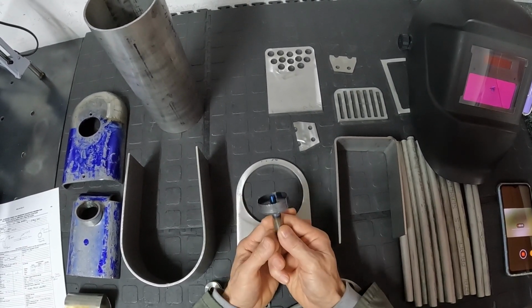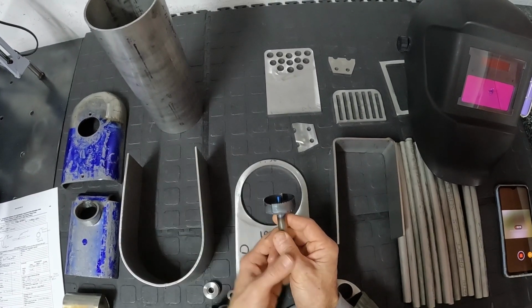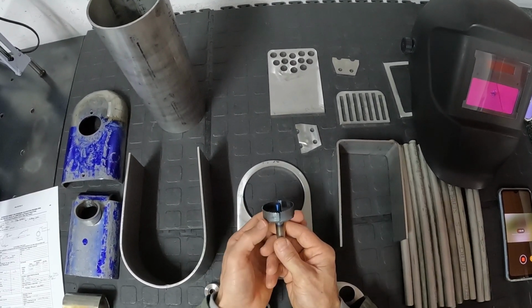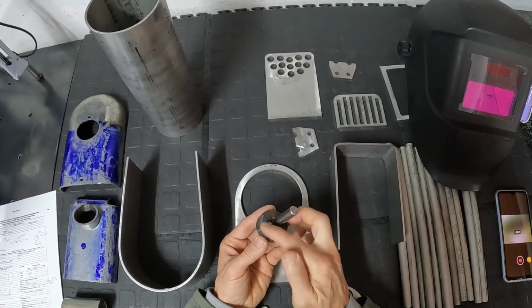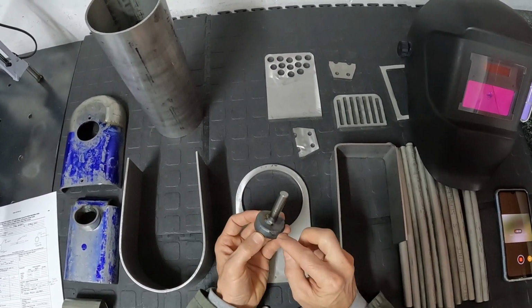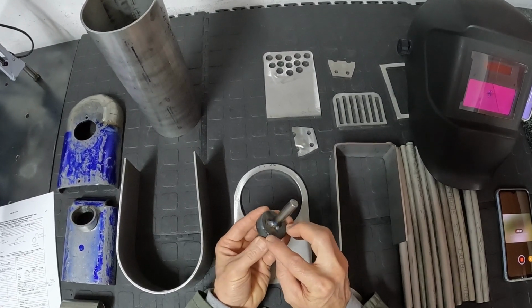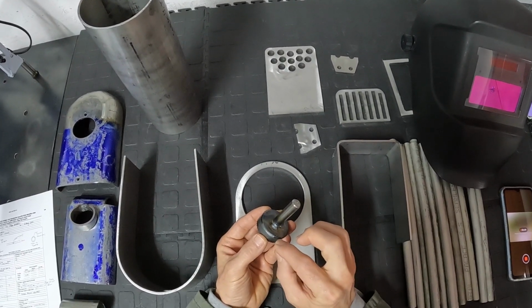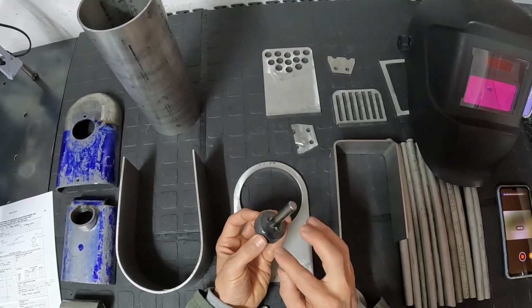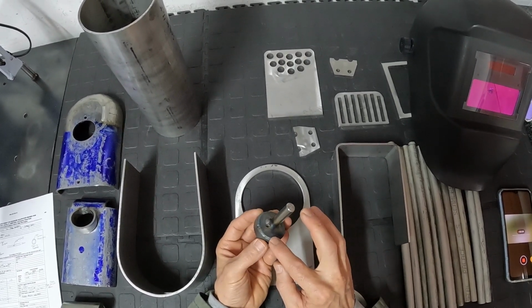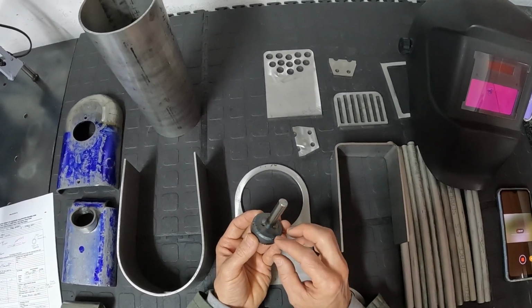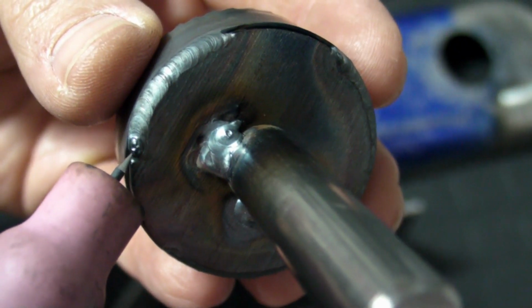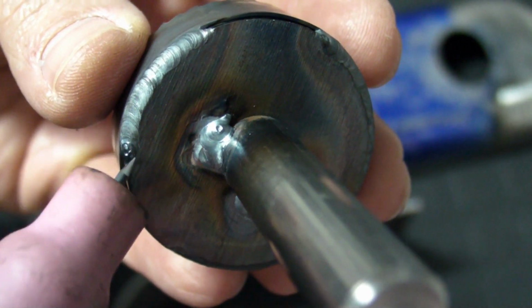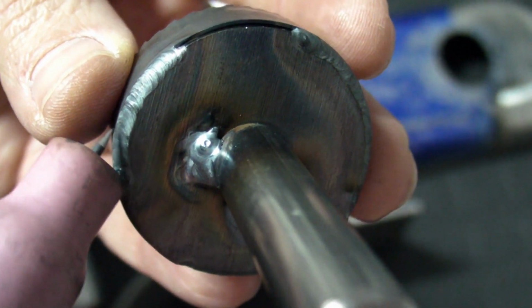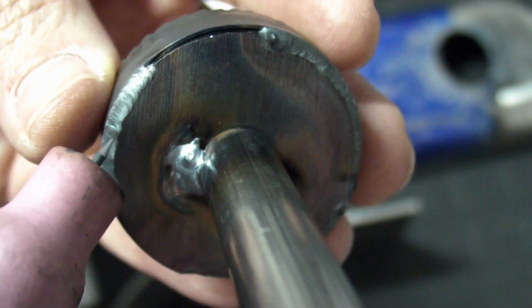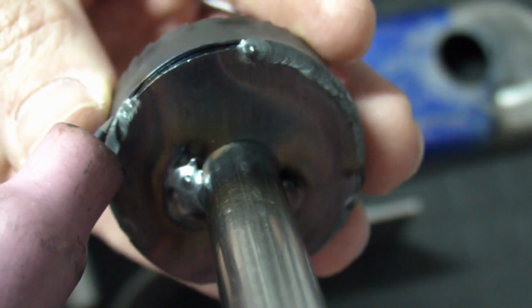If you take a bandsaw blade, and I typically use one of my broken bandsaw blades, it's not worth putting together again, and you just cut a ring with a little spigot on, then you can weld it onto the back end of the bandsaw blade. And this is a very specific type of weld. This is called a fusion weld, and I use the same process for my tubes. It looks a little bit like this. If you take the welding torch, you put the welding torch on the one side, you actually collapse the weld onto the bandsaw blade and you get a fusion weld. So there's no filler rod in this specific weld.